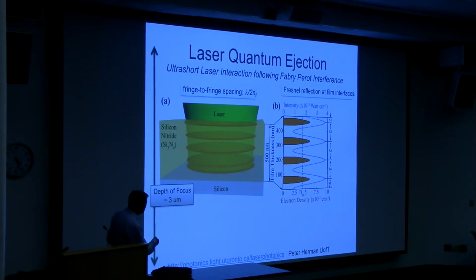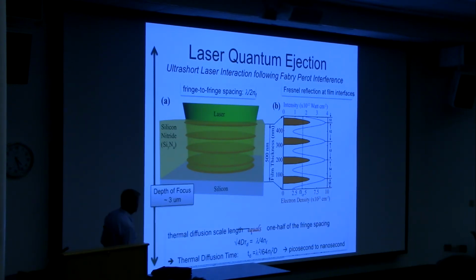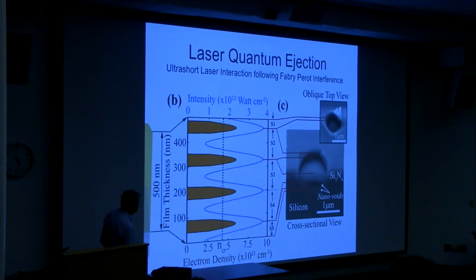These plasma disks are following the interference pattern of light, but they're narrower because of nonlinear absorption. These plasma disks are maybe 40 nanometers thick, and this depth of focus is several microns. So we've really downscaled the interaction zone along the laser propagation. These are flat pancakes, and when they explode at the right amount of absorbed energy, they peel open the material in these unique ways.